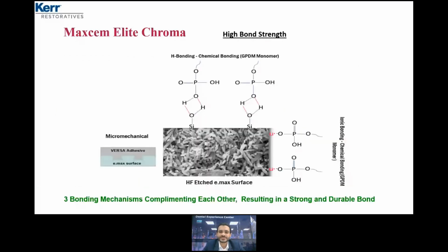Here is an example of a hydrofluoric acid etched Emax surface. First mechanism, micromechanical bonding. Second one, covalent bonding between the GPDM and the ions inside the Emax. Third one, ionic bonding between the Emax ions and the GPDM. So again, we have two ways of bonding to the tooth structure, and almost three bonding mechanisms to the restoration, regardless of zirconia, porcelain or Emax. So with both of them, we can reach high bonding strength.